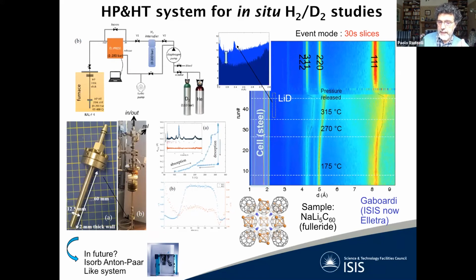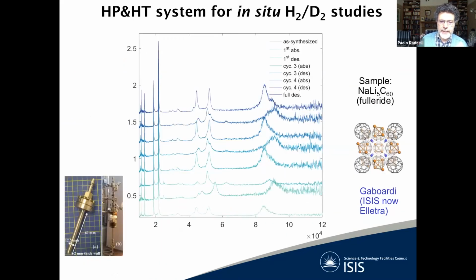at low angle, okay? And so these particular data were collected on a fulleride, NaLi5C60, with hydrogen and deuterium loading, and the data are unpublished by Gaboardi et al. And this is zooming in on the diffraction pattern. You can see the effect of the guest species is essentially all at these very long d-spacings. And this is clear because these are relatively disordered species in the lattice, and so they drop off in intensity much faster, whereas the host is essentially unchanged, and you here see the host peak on the left of the pattern.